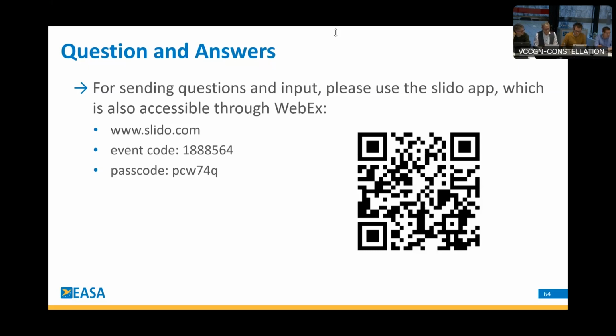Yeah, I think we need to split this into two sections, as it's also two questions. So the deep cracks, I do not know what is meant, because we saw cracks in depth in the specimen, but we did not notice through cracking. I think this was the wording. So we had a 1 millimeter laser scratch, which is already quite deep as an initial crack, and then we had some cracking. So I would say we had deep cracks on inner rings, which are the shaft specimen, but we had no through cracking. It did not develop further in a way that the shaft was completely cracked through. Yeah. What's the definition for complex loading? Yeah, we added bending stress up to 180 megapascal at the end. So the limit was 180 megapascal based on review, analysis, and simulation, and this was then added on top to the rolling contact fatigue.